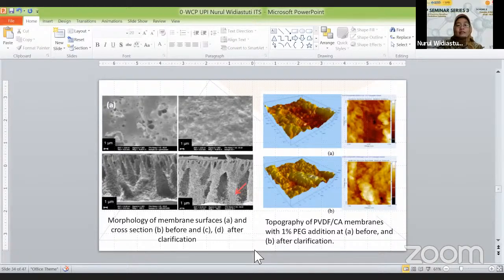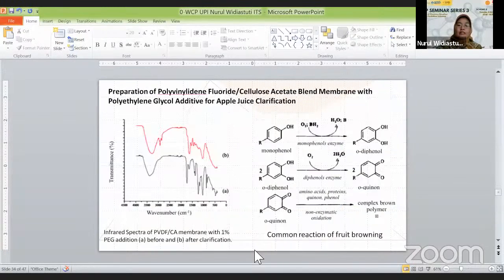As we can see here, before and after the clarification process, we see blocking on the surface of the membranes itself. So these membranes need to be cleaned or washed. And this is the infrared spectra of the PVDF-CA before and after. As we can see, the different peak here shows that this is because of the functional group from the fruit browning reaction due to the enzyme reaction.